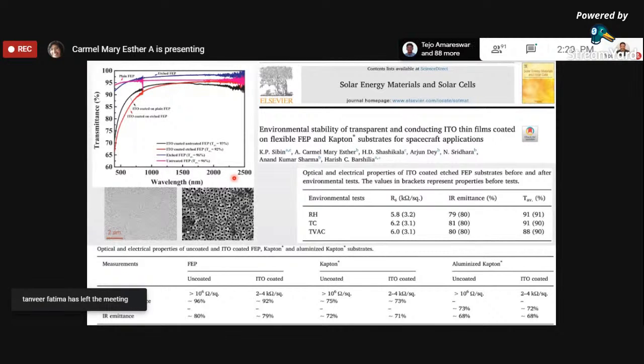So this is why this example is important. Sometimes in practical applications we may require very good adhesion of the film rather than very good transparency and optical properties. The developed coating has already been tested for several space environments like thermal cycling and thermo vacuum cycling, and we have seen the altered sheet resistance within the range which is required for our space application, and the thermo-optical and transparency behavior we have also achieved. The maximum transparency required for this kind of coating in spacecraft is 80%, so that we were able to achieve.